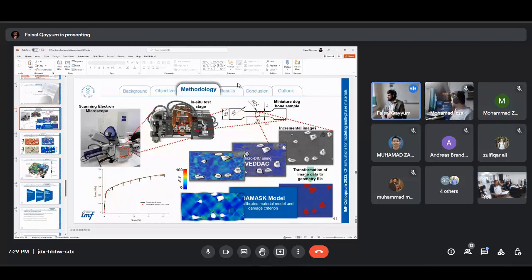When we have a picture, we are only constructing 2D micrographs, or the geometries. We are not actually constructing 3D geometry. The script which we have, we have not done that yet. For 3D RVEs, what we usually do is collect microstructural data, let's say the grain size and the percentage composition and so on. Then we use Dream 3D to construct virtual microstructures for us. So the overall microstructural features resemble what we have in the actual material, but they are not specifically that picture converted into a micrograph. So these are two different schemes of constructing RVEs.